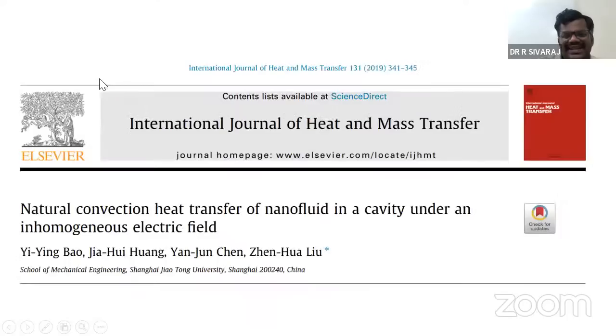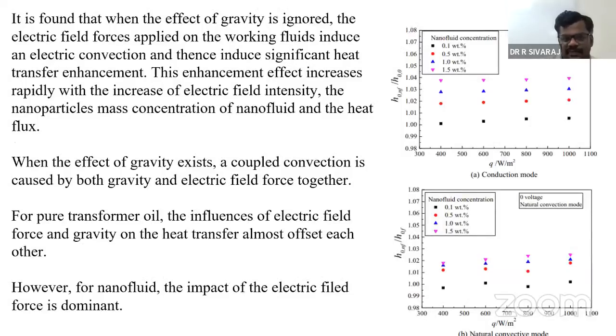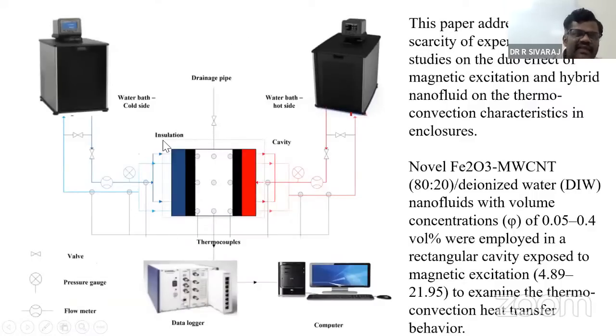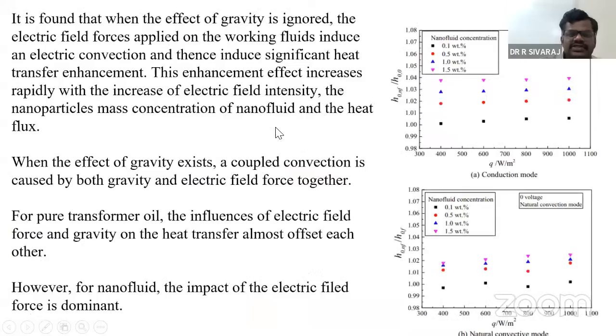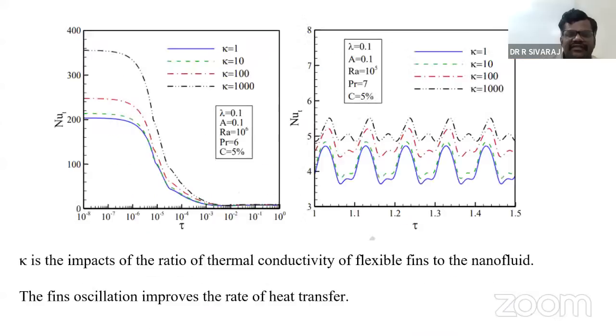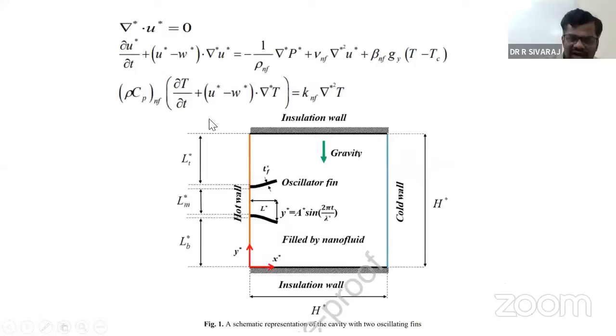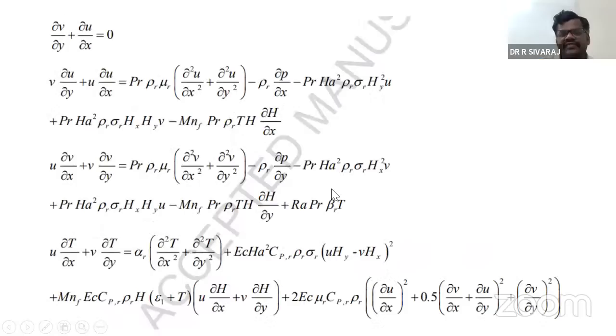And then what are the results we want to analyze for the theoretical situation and the practical situation. For example, here the cold wall is maintained through the water cold bath side with these valves, pressure gauge and flow meter. The hot wall is maintained through the water bath hot side. In the theoretical situation, we just take the left wall as the hot wall and the right wall as the cold wall. The top and bottom walls are just insulated walls. Then the boundary conditions are through the values we measure in nature, through direct imposition of a physical component.